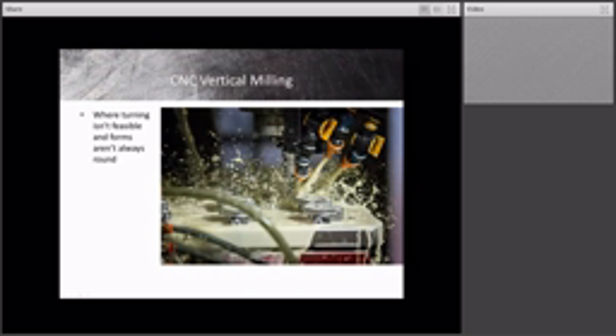So in cases where there is no opportunity to turn the part, in other words, the part can't rotate because of the configuration or because of the desired configuration of the feature that you want to place into the part, you might want to do vertical milling. We do a significant amount of vertical milling that allows us to make oblong shapes or cut S-type or infinite shape grooves into flat components, and allows us to do a variety of things, up to and including brushing of components, which is something that we've only just recently gotten into using as a prep for gears.